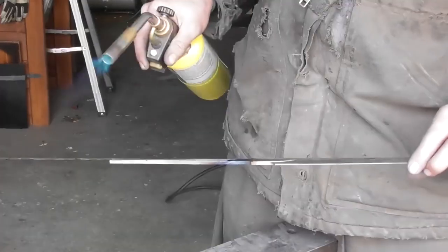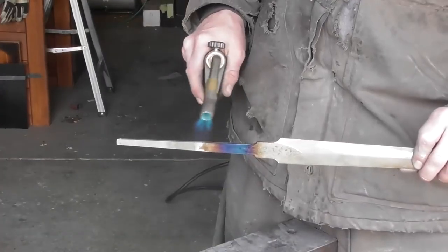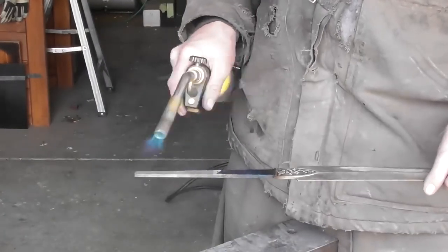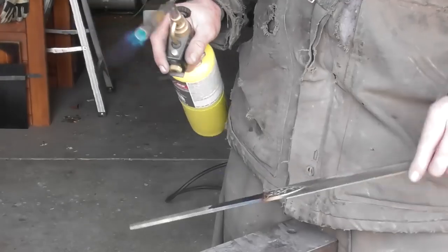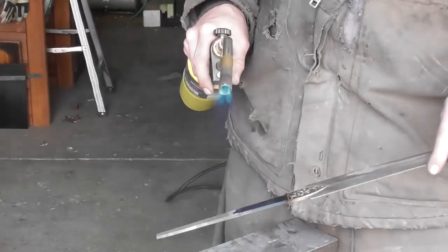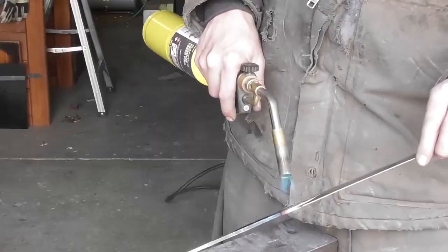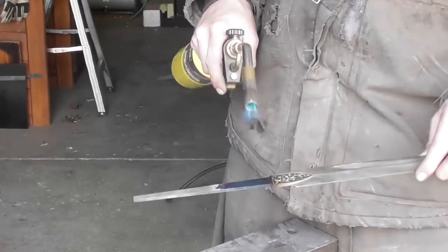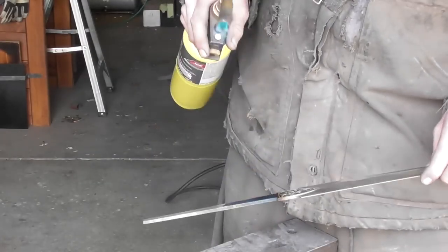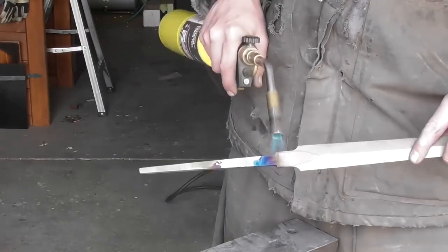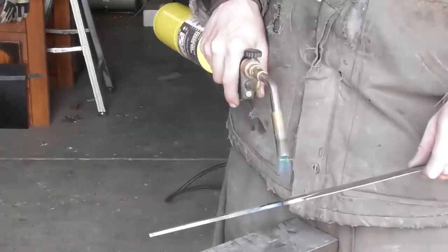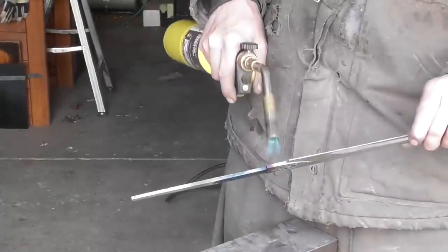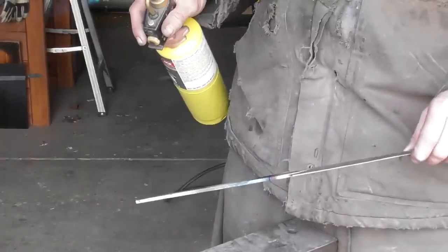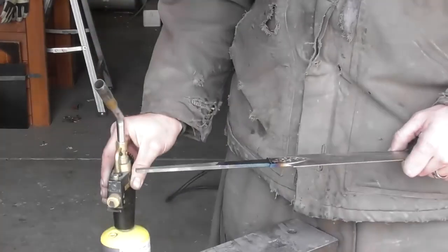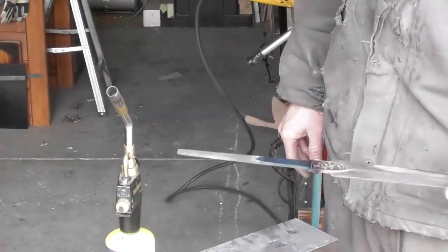That's a high stress point where getting at that spring temper will really toughen it up so that if it gets hit against something, it's really going to be unlikely to break. One of the cool things that I like about this video is you can actually see the high carbon steel changing colors, whereas the mild steel is going to stay that gray color because of the different carbon compositions in there. Mild steel doesn't have enough carbon in it to be hardenable, whereas the high carbon steel is hardenable.